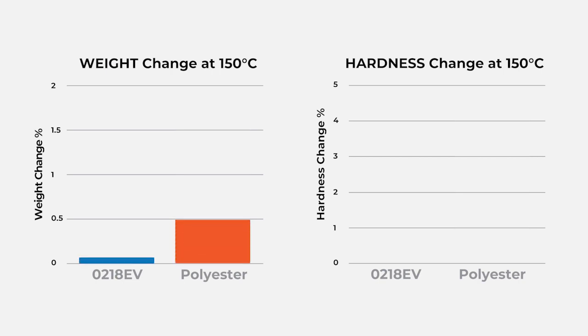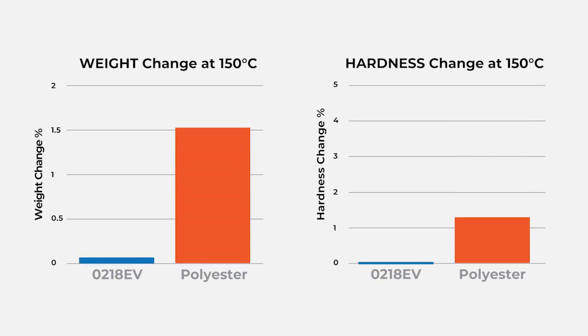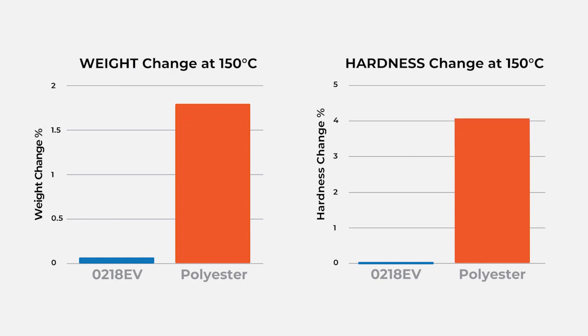potting compound. In this example, we have thermally stressed samples of EPIC 0218 EV epoxy and a leading polyester at 150 C for 500 hours. When you evaluate weight loss and hardness change, you can see 0218 EV maintains its weight more consistently than polyester. The greater stability of the 0218 EV epoxy is due to the better stability of its molecular structure compared to polyester.